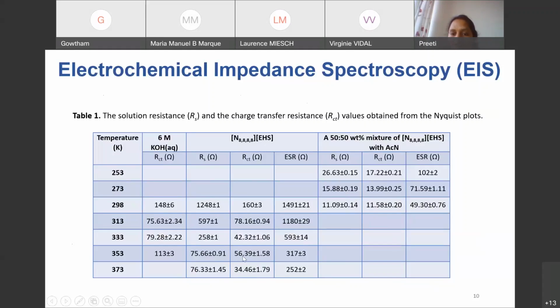It is even 56 at 80 degrees, 42 at 60 degrees. So it's an indication that at high temperature, this electrolyte behaves even better than the aqueous electrolyte at room temperature. And also, if we want to use it at very low temperature, which is minus 20 degrees, we can use the binary mixture of this ionic liquid. So it gives us a very wide range of temperature to use this ionic liquid or electrolyte.